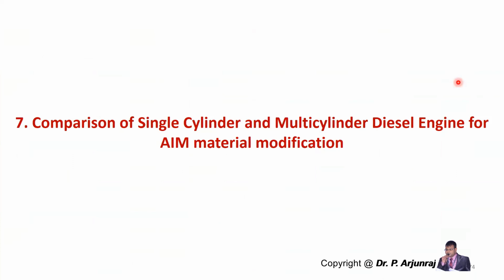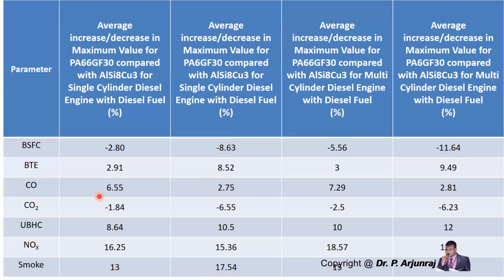And this is the comparison of single-cylinder and multi-cylinder diesel engines for air intake manifold material modification. And these are all the parameters, BSFC. When you take BSFC, the average increase or decrease in the maximum value for PA66 glass fiber 30 when compared to aluminum for a single-cylinder diesel engine is minus 2.80%. Similarly, it is minus 8.63% for PA6 glass fiber 30 when compared to aluminum. This is for a single-cylinder engine. For a multi-cylinder engine, it is minus 5.56% and minus 11.64% in the case of BSFC.